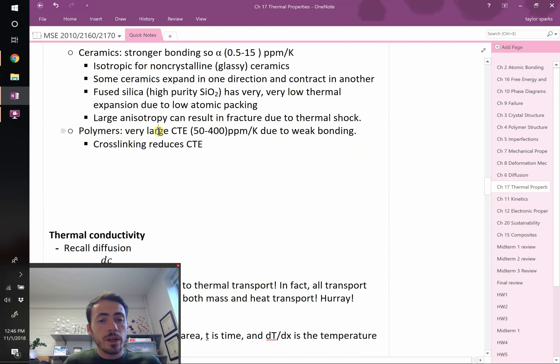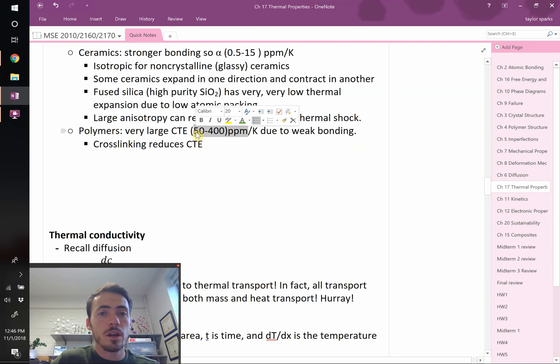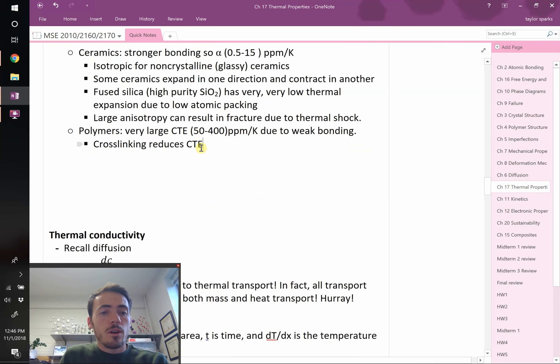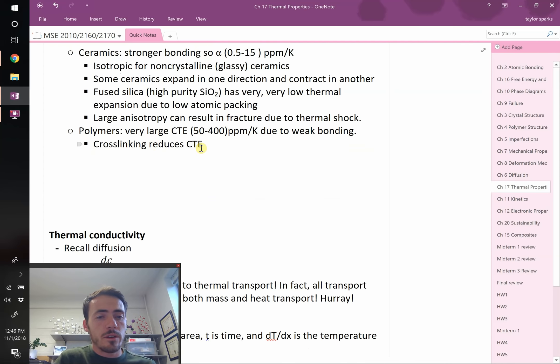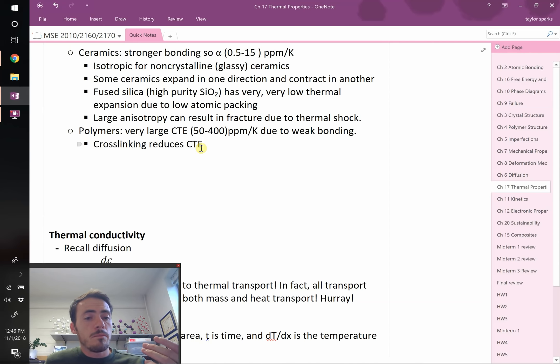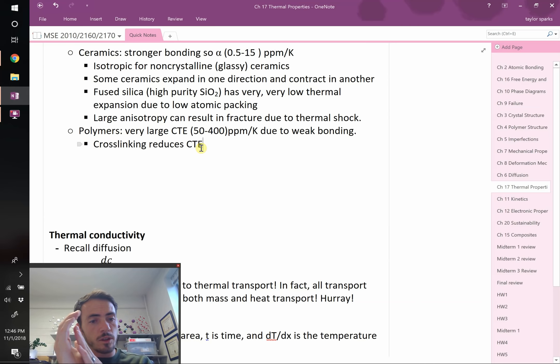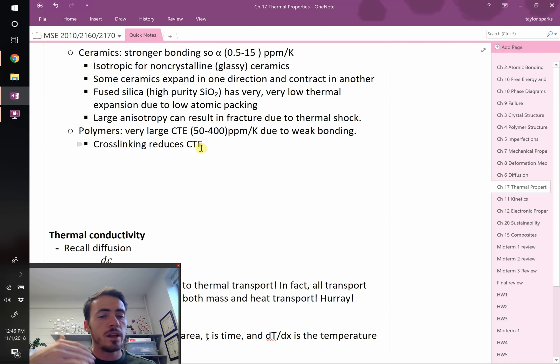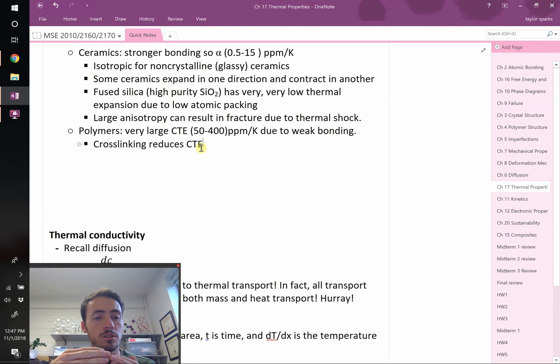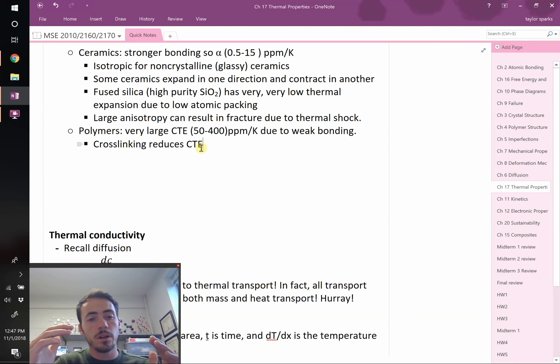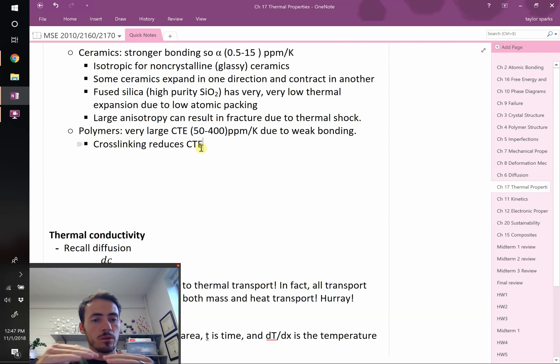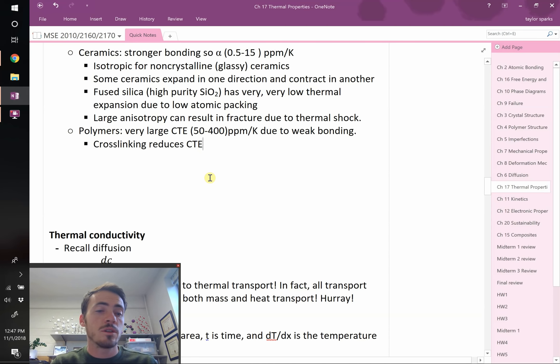Polymers are weakly bonded via van der Waals forces, giving a shallow asymmetric potential well, which means very large thermal expansion — 50 to 400 ppm per Kelvin. A real project example involved polymer liners inside steel tankers for shipping acid. As temperature fluctuated between day-night cycles and different climates, the polymer wanted to expand and contract a lot but the metal didn't, creating thermal mismatches that caused thermal stresses and breaking. This was eventually fixed.